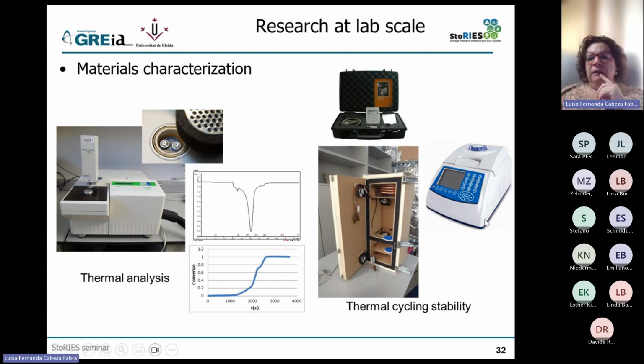The equipment on the right is a commercial thermal cycler used in medicine usually, that we discovered by chance, and we use today to thermally cycle, for example, our PCMs. The restriction here is that this only heats up to 80 degrees C, because of course it was developed for medicine, which is their maximum temperature. But for example, for building applications or even for cooling, it works.